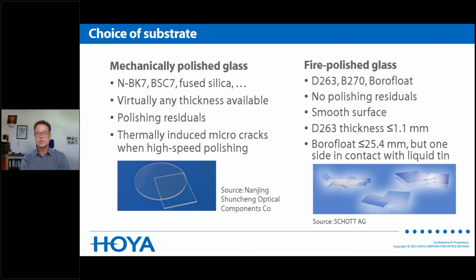So in recent years, filter companies looked at fire polished glass or float glass like D263, B270 or borofloat glass. There are no polishing residuals necessary, or they do not occur. They have a very smooth surface for good and uniform growth of the thin film layers. A drawback is that, for example, D263 is only available in 1.1 millimeter thickness as a maximum.